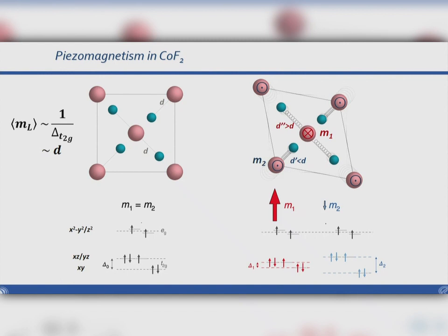And now when you apply strain, you make this bond here larger, and this bond you make shorter. So that means for the sublattice that is in the center, the cobalt atoms in the center of this compound, they have a positive change in the local magnetic moment, while those ones have a decrease of the local magnetic moment. So therefore, you unbalance the magnetic system, so that at the end of the day, you end up with a net magnetization. So this is a ferrimagnet, right? You don't change polarization directions, you change the local magnetic moments.